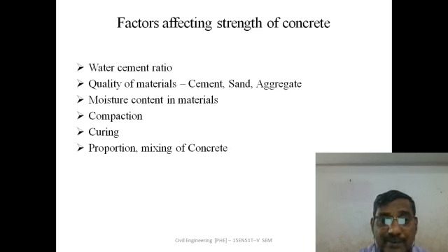Next, the material quality, that is cement, sand, aggregate. If the cement used is fresh, we will get high strength. If the cement is stored for more than 3 months, 6 months or 1 year, then the strength decreases. It is observed that for 3-month storage of cement, 15 to 25% of the strength of the concrete will decrease. For 6 months of storage, 35 to 45% of the strength will decrease.